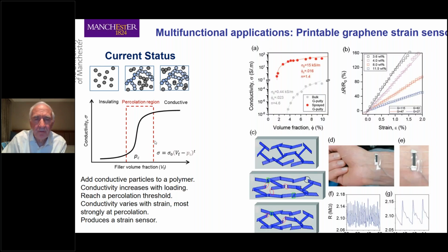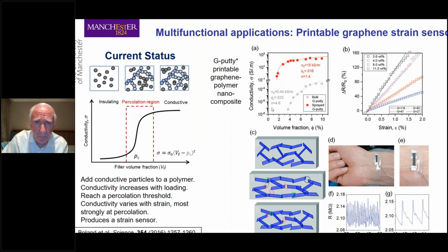And here's one example of one of our publications where we looked at what we call G-putty, which is graphene dispersed in a silicone polymer, which makes a very strain sensitive material. If you plot the conductivity of this material on a log scale against the volume fraction of graphene, you see that the conductivity is very low to start off with, then shoots up at about 3% loading, and then goes to a plateau value. And the sprayed material, the painted material, is actually much more sensitive than the bulk material, which is quite nice. The work was published in Science and Small.